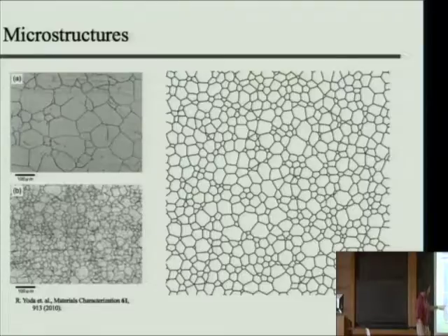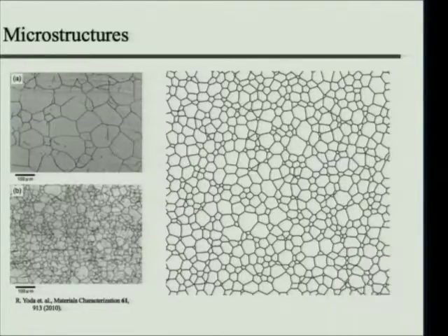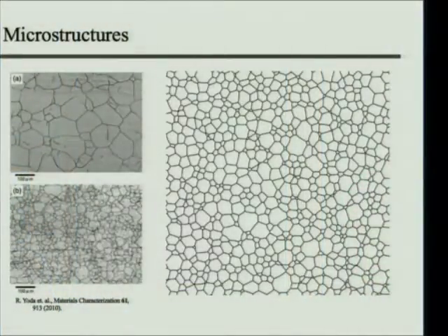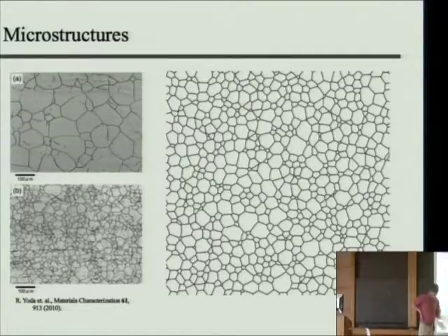It's not just as simple as that. The rate of the kinetics by which this process happens depends exponentially on the temperature. It's a Boltzmann relation, where this is the temperature, and this is proportional to the rate at which this process happens. Arrhenius law, thank you, that's right. It goes as an Arrhenius law. And so this happens all the time. It happens at room temperature also. It's just the kinetics are so slow you never observe it for steels.